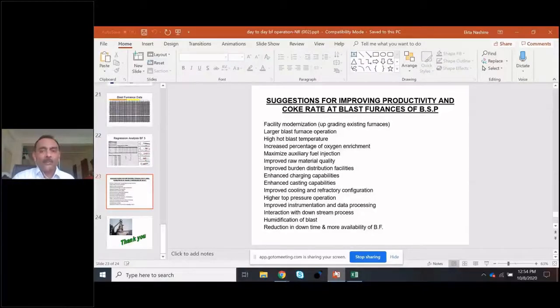Auxiliary fuel injection we have to maximize. During this suggestion, I want to say one thing. Coke is a very, very important raw material in the process. You cannot remove all of the coke from the furnace, because at the lower level, when all the non-coke has melted, only coke remains in a solid condition. Through the permeability of the coke, the liquid slag and liquid metal come downwards into the hearth. So at the lower part of the furnace, in front of the tuyere, you need coke to be in a solid state. But you cannot remove all of it. You cannot make it zero coke.